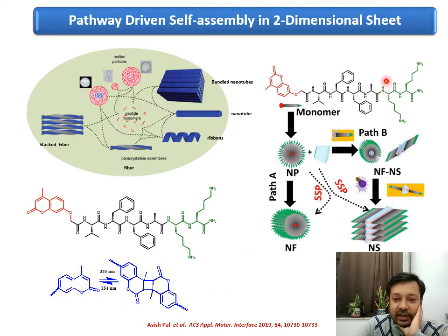And what it does is that if you take only this peptide amphiphile, of course, they will go for an on-pathway metastable nanoparticle, which will eventually form nanofiber. However, if you sequester using a gamma cyclodextrin moiety followed by light irradiation, it forms not only fiber, in this case it forms fiber, but if you irradiate it, it actually forms very nice 2-dimensional nanosheets.